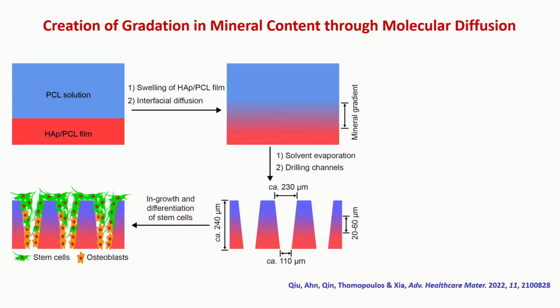And this is basically a piece of film, and then we can come to IEN to do micromachining. So we can generate arrayed channels all the way through this film. Eventually, we are going to just use this film as the scaffold. At the bottom, you are going to have high concentration of hydroxyapatite, and at the top you are going to have polymer, and in between you are going to have a transition in terms of mineral content.